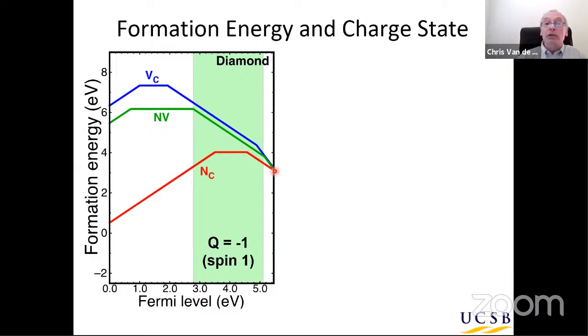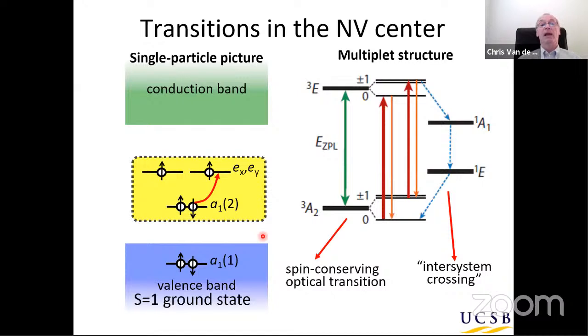Now, in order to guarantee overall charge neutrality, the vast majority of the nitrogen will need to be in the neutral charge state. And as you can see, by coincidence, or maybe not, the Fermi level gets located smack in the middle of this green region where the NV center is in the correct charge state that gives us that spin 1 state. Okay, so that's a fortunate event in diamond that gives us that correct charge state.